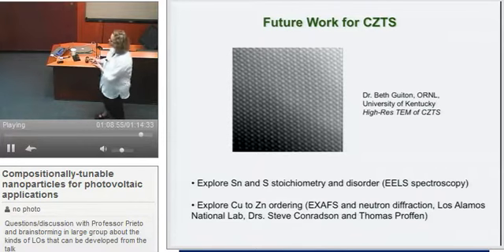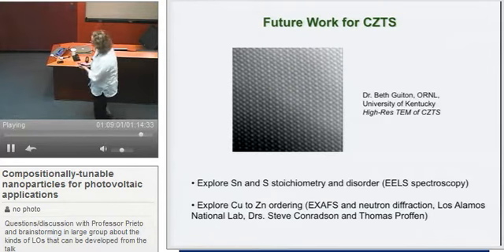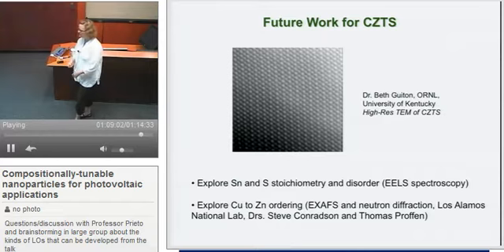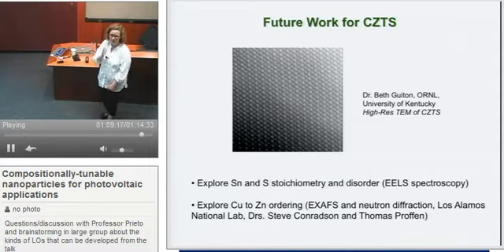Now, we've also been doing a lot of work with my collaborator Steve Conradson and one of his colleagues, Thomas Proffen, at Los Alamos National Lab. And he does X-ray absorption spectroscopy, which is really useful because it's tunable to the element that you're looking at. Now, what I have not talked at length about is that copper and zinc you can't tell apart by X-ray diffraction because they're right next to each other on the periodic table. But with XAFS, you can get a picture of local structure. So it's not long-range structure, but you can see what's bonded to what around the copper atoms.